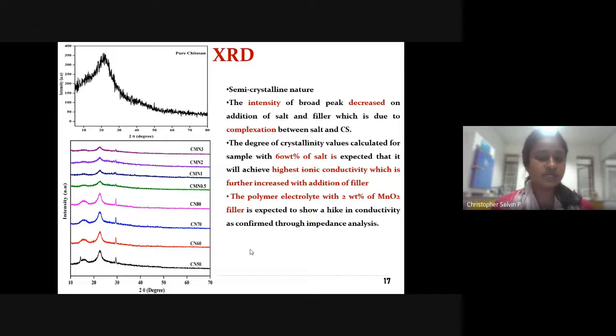The polymer electrolyte with 2 weight percentage of MnO2 filler is expected to show a hike in conductivity, which is being confirmed using impedance analysis.